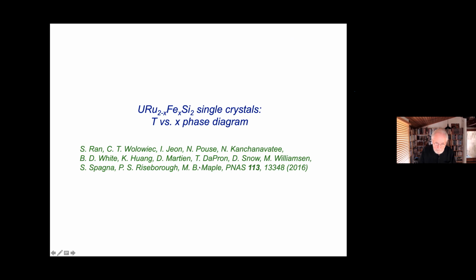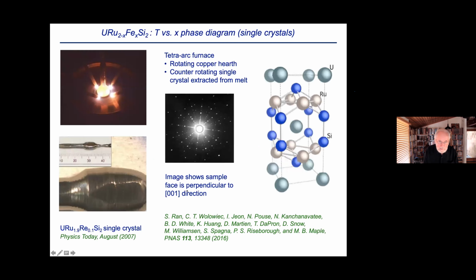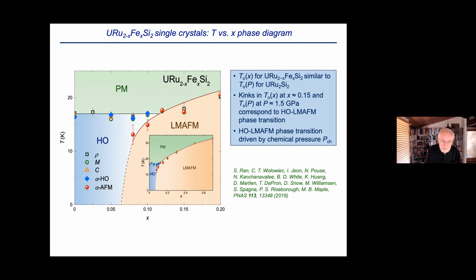We first did this in polycrystalline specimens, and then we changed to single crystals as we got more deeply into trying to understand what was going on. This is the first paper in PNAS in 2016, where this was published. This is just showing you what one of the single crystals looks like. It's grown in a tetra-arc furnace by the Czochralski method, so it takes a lot of time to grow these. You can't grow a lot of specimens, but this is what we found for the single crystals.